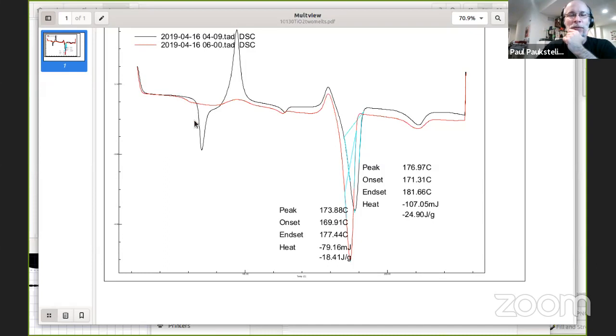And so there's this really, I mean, this kind of thing happens in first melts, but it's never this pronounced. And so, you see this is the cold crystallization peak. This thing here is odd. This you always see in PLA. This is the melting temperature of PLA right here in this case. And this thing, that's also due to the titanium dioxide.